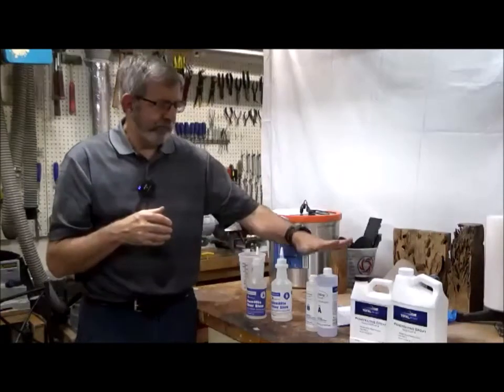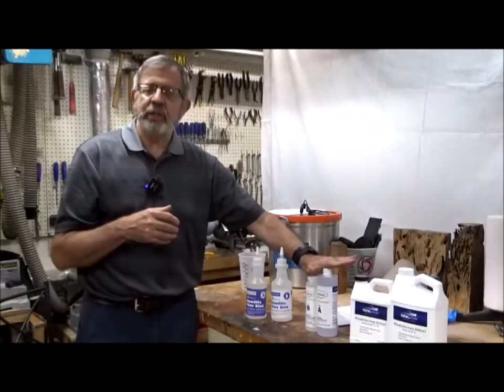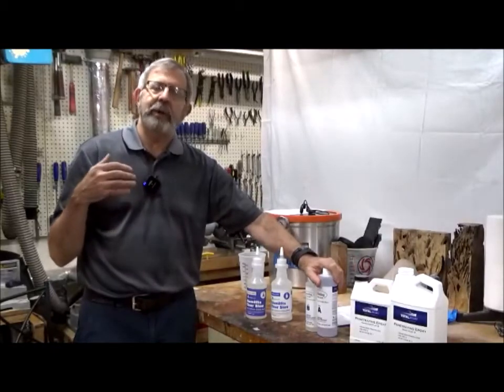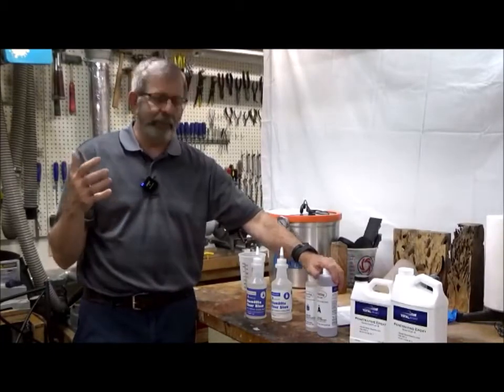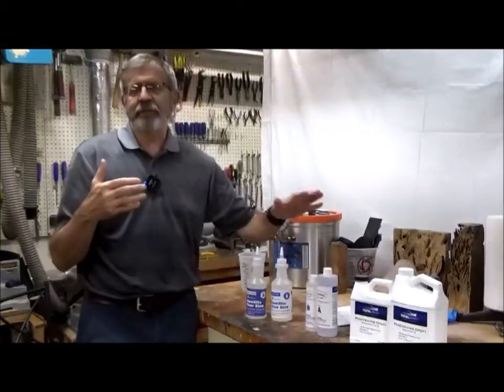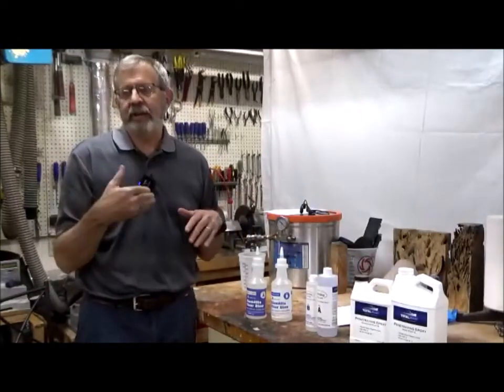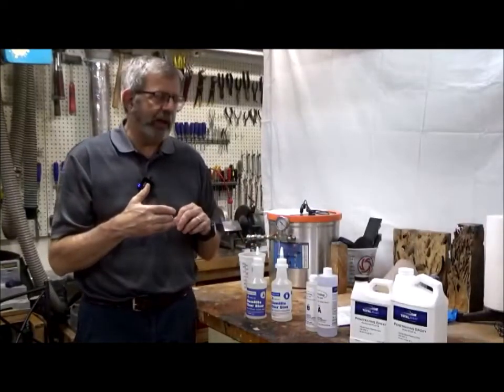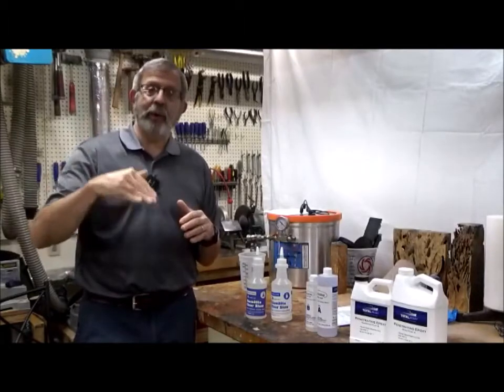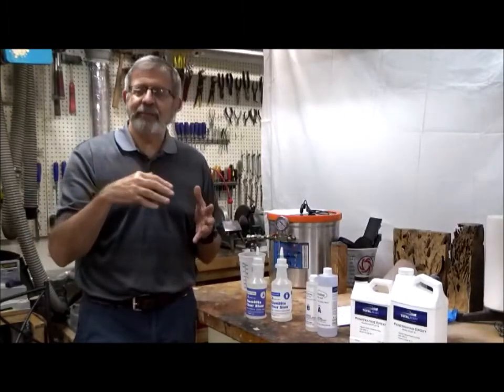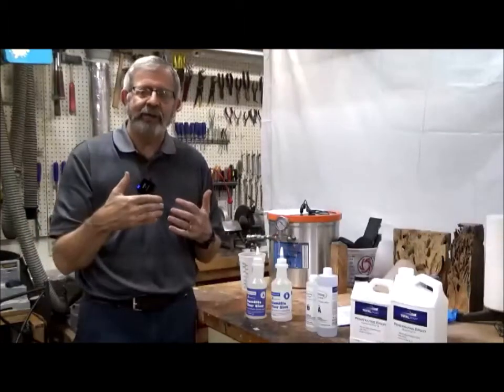So there are other epoxies that you can use. I used an epoxy called Liquid Diamond that is somewhere between this and this. It's set in about a day, and you could turn it after 2 days. Again, you have to be careful where the thickness goes. But the advantage is that if you have something that sets in hours rather than minutes,